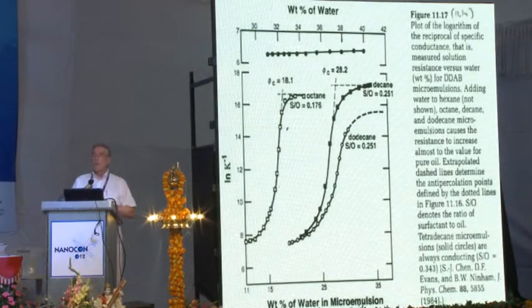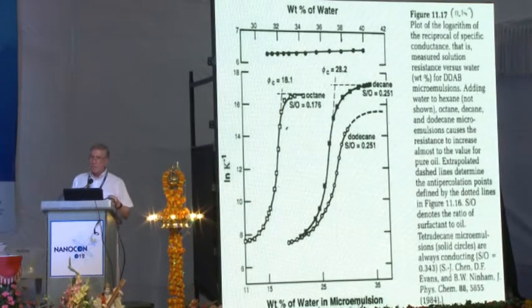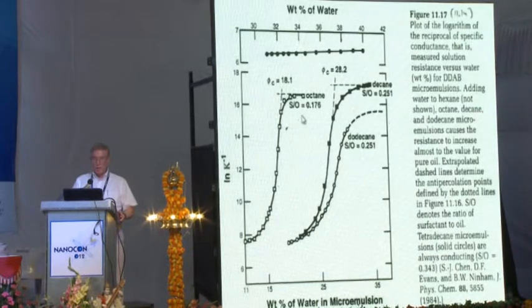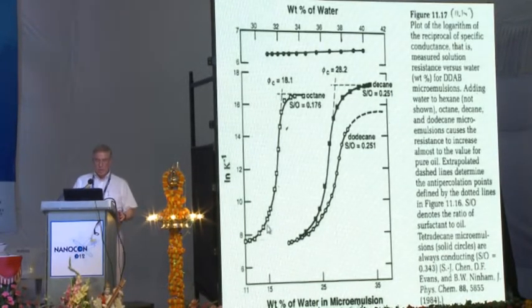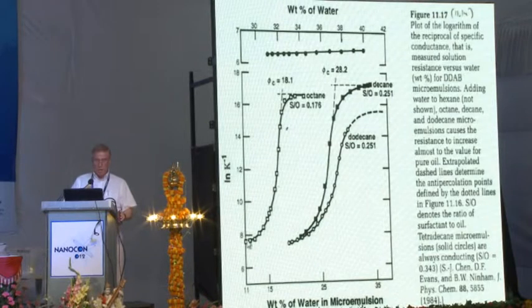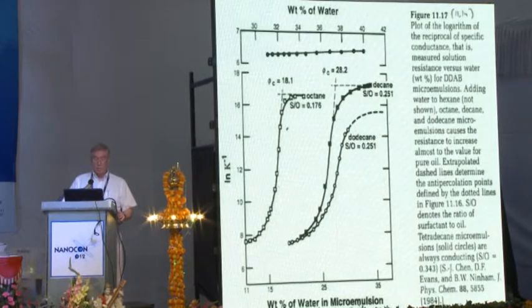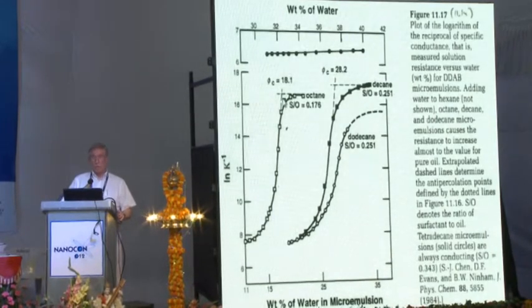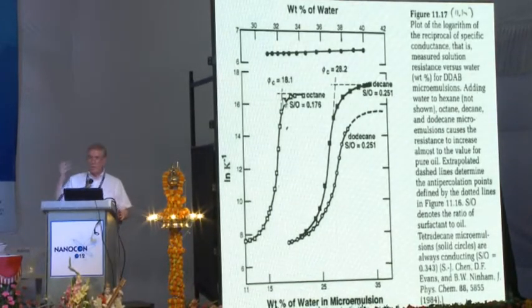What they did was they measured the electrical conductivity, or rather the resistance, as a function of the addition of water. So if we look at this one here, octane, which you see here at low water concentration, the conductivity is high, the resistivity is low, but as you add water, the resistivity goes up enormously, orders of magnitude. Now, if you think of it, this is really unusual. You add water, which is conductive, and the system becomes non-conductive.